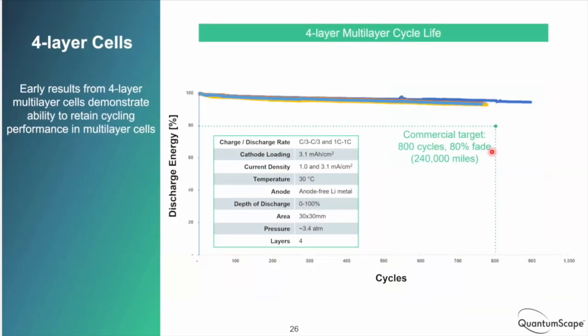So we have made four-layer cells and cycled them and shown that the cycling is consistent basically with the single-layer cells. The first four-layer cells we were making were smaller areas. These were 30 by 30 millimeters. We tested these at C/3 and 1C rates, again with a similar cathode loading, near room temperature, same pressure, but four-layer cells, and showing that we can exceed this commercial target of 800 cycles to 80%. These cells were all exceeding that pretty comfortably. So this was an interesting early demonstration that multi-layering could work.